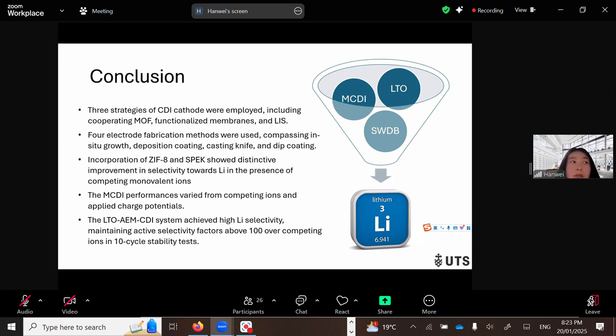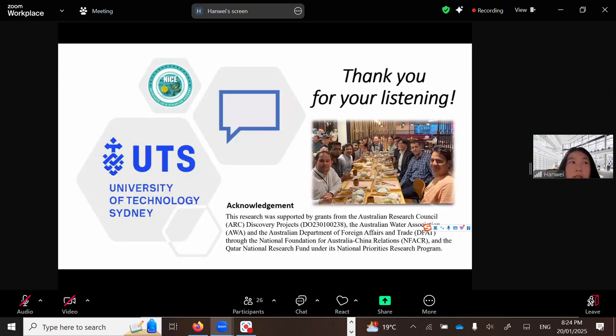But the best one is still the lithium ion sieve LTO. The LTO MCDI system achieved super high lithium selectivity, and it maintained an active selectivity factor over 100 during the 10-cycle stability test. Finally, the MCDI performance also varied with the competing ions and applied charge potentials. These are mainly my PhD research and my findings. Thank you, everybody, for listening to my presentation.